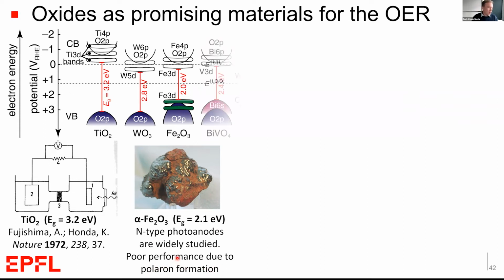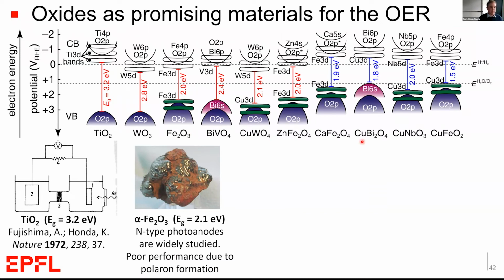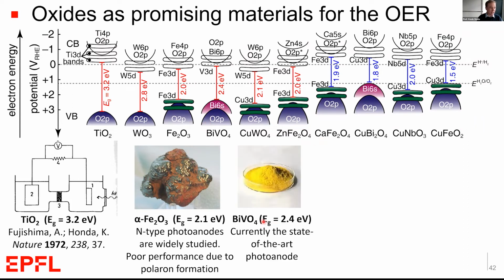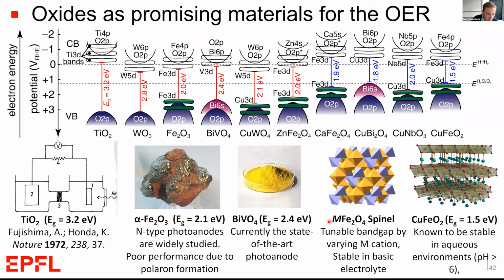So more recently, investigators have looked at a wide variety of ternary-based oxides, including bismuth vanadate, which has a little bit too high band gap, but still works probably the best, and combinations of iron spinels or delafossite type materials that have been looked at in our group. But I just want to give you an impression of one of the strategies that we have to use with these oxides to get them to function well.